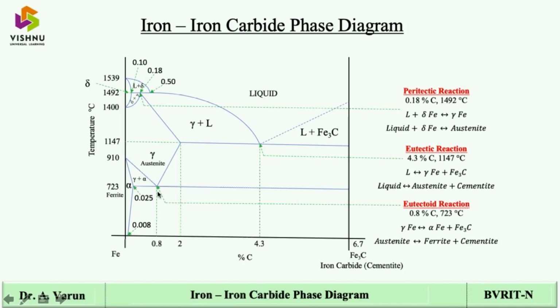So this is what you are supposed to remember. Simply three invariant reactions. One at 0.18% of carbon, which is a peritectic reaction at 1492 degrees centigrade, wherein you'll have liquid plus delta iron transforming into austenite. Then next, at 4.3% of carbon, eutectic reaction, at 1147 degrees centigrade, liquid will transform into austenite plus cementite, and that mixture is called ledeburite.